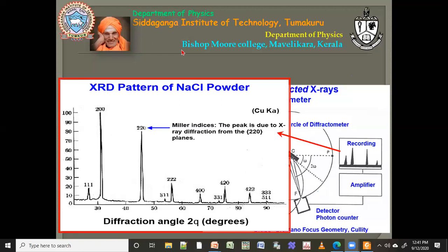At 2.5 it is lower symmetry. So that is where you can use X-ray also as one of the tools, because not everyone can do Mohr salt titration. Most people from a physics background find it very difficult. I am from a physics background, but somehow I learned a little bit of chemistry, so I can do Mohr salt, but not everyone can. So this is just by the synthesis method.